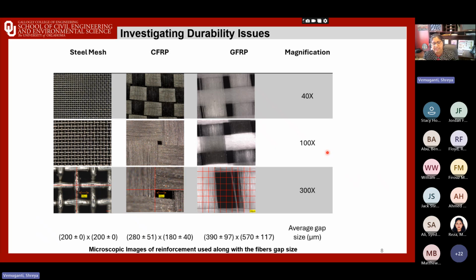For these interfaces, the actual reinforcement that you're seeing within are these types of reinforcements. We've used steel mesh, carbon fiber, and glass fiber polymers. If you look at these pictures taken with a microscope, you see that the steel mesh has a 200 by 200 micron opening size, the CFRP is 280 by 180 micron, and GFRP is 390 by 570 micron. So these are a variety of materials as well as opening patterns.